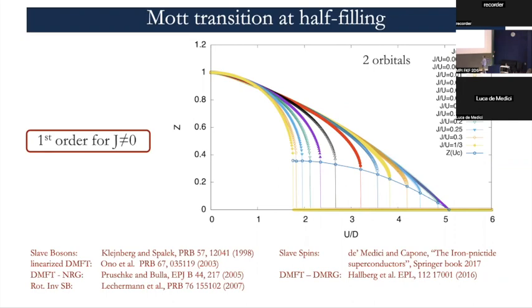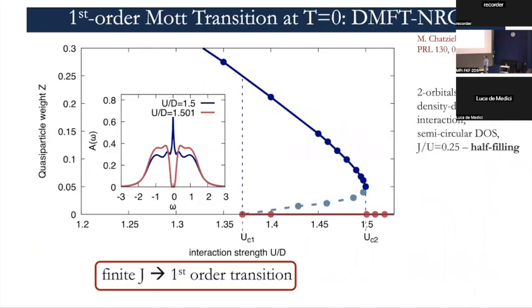So there is a jump. And this is true for the density-density interaction that we're using, but it also holds true for the more realistic Kanamori form of the interaction. This is seen through many different methods. What we will do is clean up this issue by solving dynamical mean field theory here with numerical renormalization group, which really captures the physics at low energy very neatly. And we have cross-checked all our results with continuous-time quantum Monte Carlo and exact diagonalization, so it's a symphony of methods that is really coherent, and we can enter into this if you need.